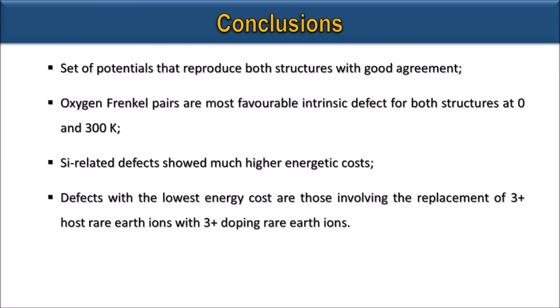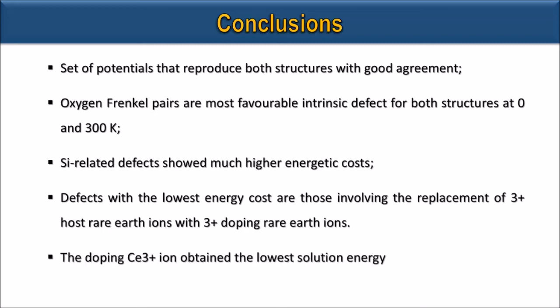And for extrinsic defects, our calculations show that the most energetically favorable defects are when our matrices are doped with rare earth ions 3+, replacing the host rare earth ions. And doping with the cerium 3+ ion obtained the lowest solution energy, which may be likened to the difference in its ionic radius in relation to the other rare earth dopants. And we expect more promising results in relation to extrinsic defects in these silicates.